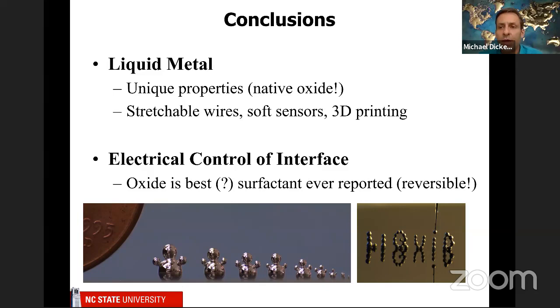So to conclude, I hope that liquid metal has shown you these kind of interesting properties, that there's some extreme properties, kind of the best combination of conductivity and stretchability, the highest surface tension known to man. And this leads to some really unique opportunities, such as stretchable devices, soft sensors, and even 3D printing at room